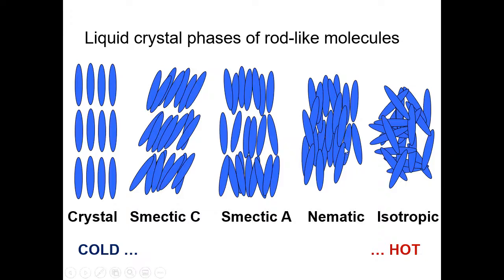Okay, if you keep cooling, some rod-shaped molecules have another phase, a set of phases called smectic phases that are layered. And so it has translational order along one axis, but then it's disordered in the plane. So it's like stacked two-dimensional fluids. If you do X-ray scattering experiments, for instance, you can see a clear signature of regular spacing along one axis, but it's liquid-like in the other two directions. A smectic where the average orientation is perpendicular to the layers is called a smectic A. But the materials can also tilt, and some of them have another phase, a tilted phase called a smectic C.